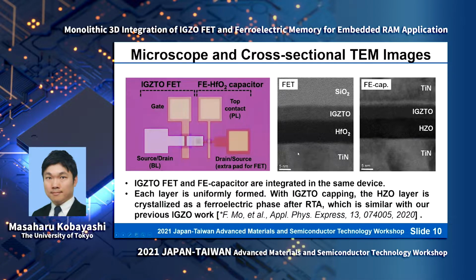And this graph shows the cross-sectional TEM images of the transistor side and also the capacitor side. For the transistor side, we can see that the gate insulator hafnium oxide is amorphous, and the IGZTO channel is also amorphous. On the capacitor side, this is the ferroelectric hafnium oxide, and it's fully and uniformly crystallized. And the IGZTO channel material is also kept amorphous. So the device is very well fabricated.